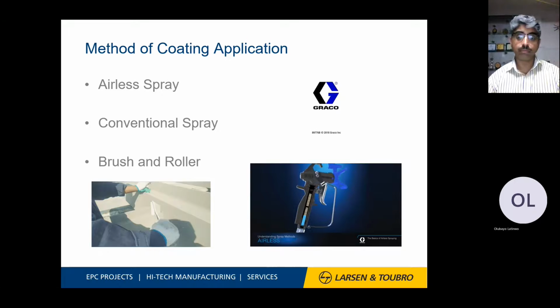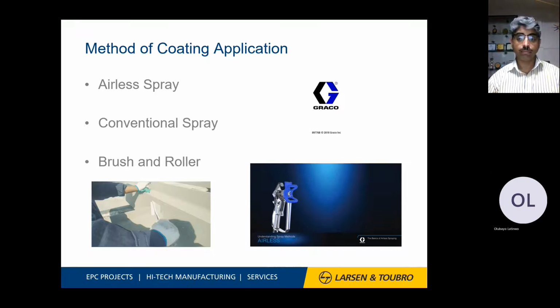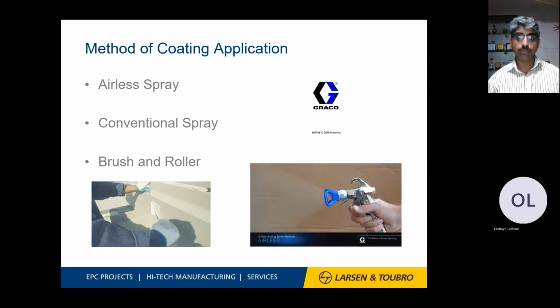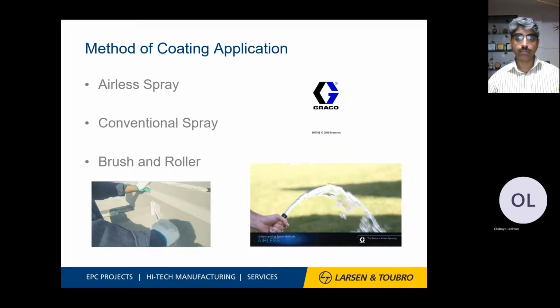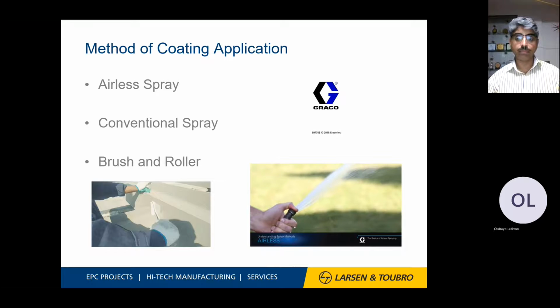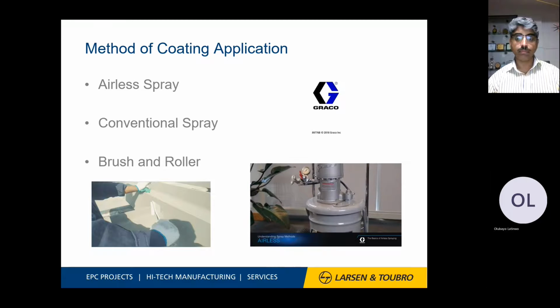Airless spraying achieves this speed by atomizing or breaking up the fluid into small droplets without the use of compressed air. Instead, fluid is pumped under high pressure through a spray tip. The fluid emerges from the tip as a high-speed solid stream, but when that stream hits the air, it becomes disrupted, and the fluid separates into very small droplets that form the spray pattern. If you've ever placed your finger over the end of a running garden hose, you created a very simple form of airless spray. Since 1958, when Graco invented airless spraying, professional contractors have preferred this method of spraying for many